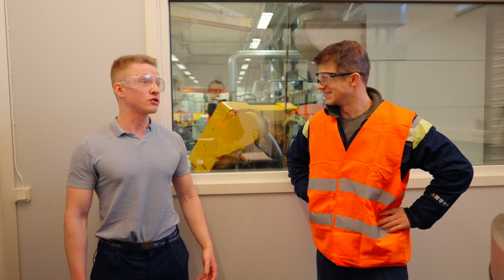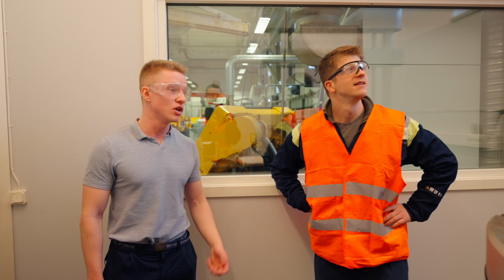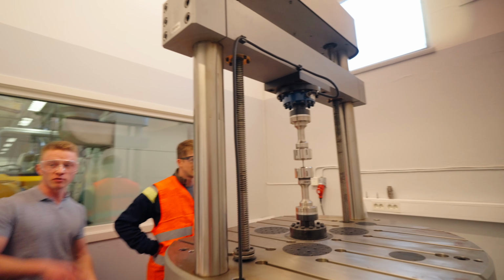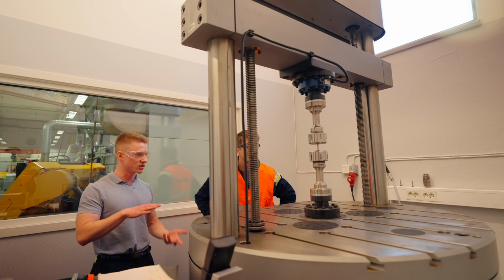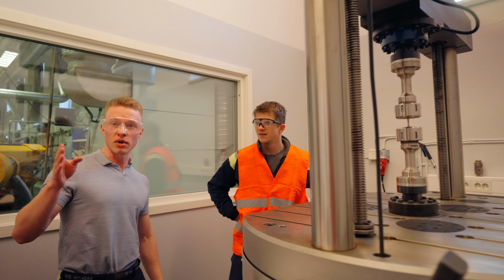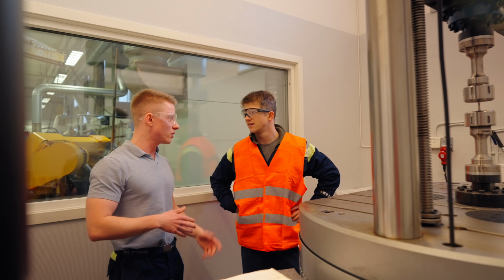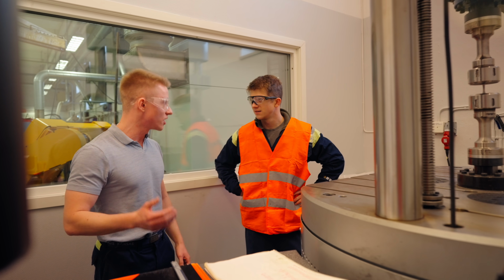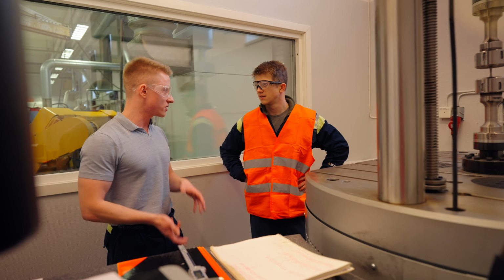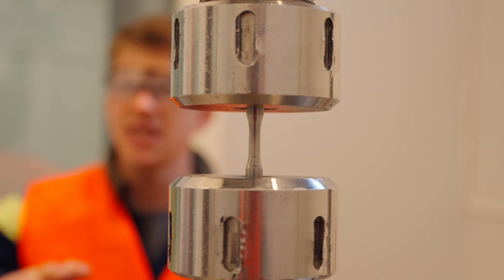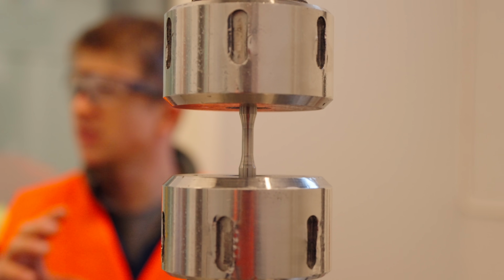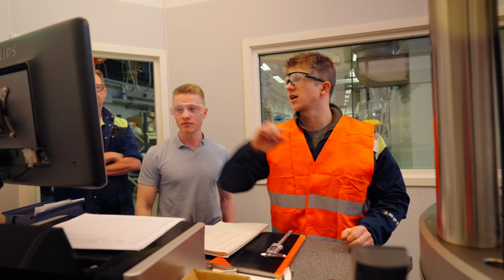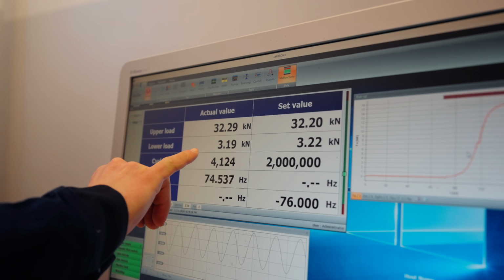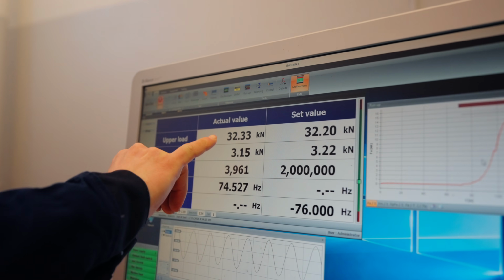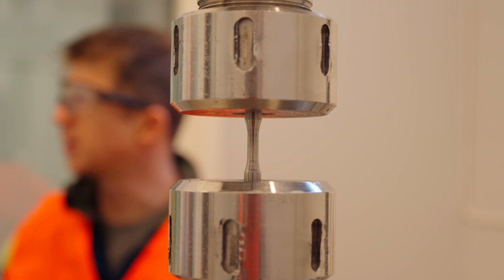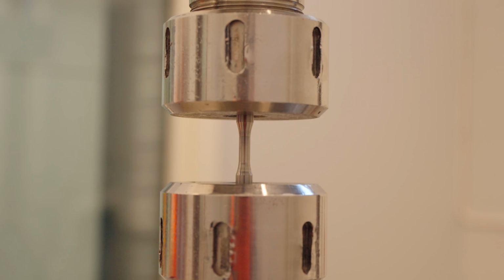Oh, thank you. So this is a high cycle fatigue testing machine. More or less what this will be doing is that it will vibrate at about, I think, 70 hertz. And it will apply a force of between 3 to 32 kilonewtons every time, 70 times a second. So there's a hydraulic cylinder beneath this that is now vibrating 74 times per second with 3 tons of tension on the part. And after how much time is this likely to break? I mean, it depends, can take a few minutes up to a few hours.